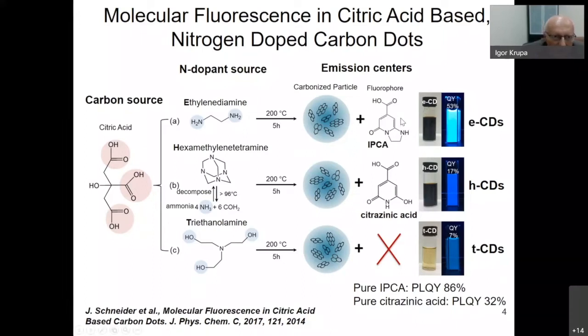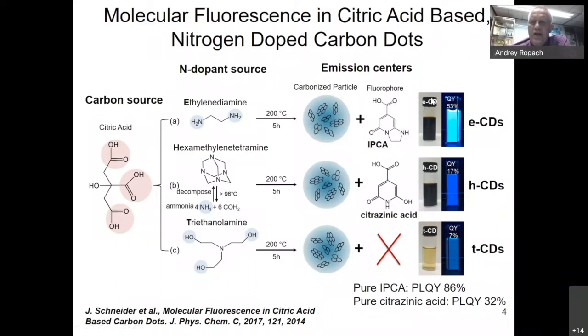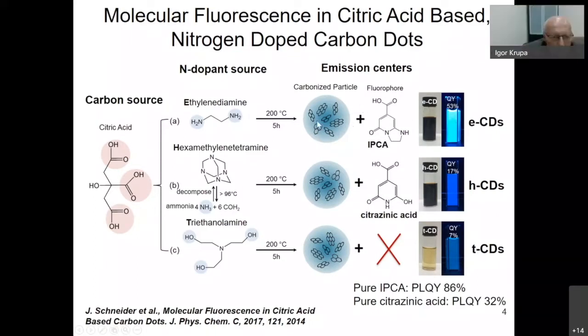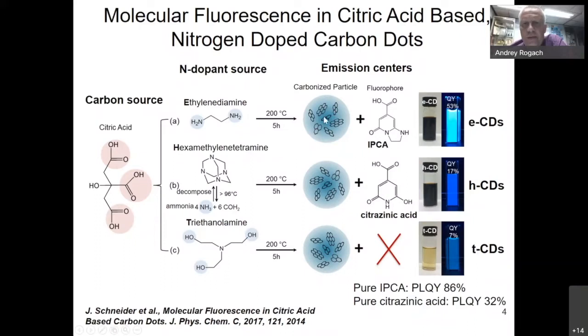I think it also depends on how much you carbonize them, right? If you put them under very harsh carbonization conditions, you will also carbonize the fluorophore itself. And then you end up with a carbonized particle anyway. So if you really want to make sure you make carbon dots at the end, you may want to treat them at even higher temperatures. Maybe many people use 250 or 270 degrees. And then the actual structure of this precursor does not matter, as you mentioned.